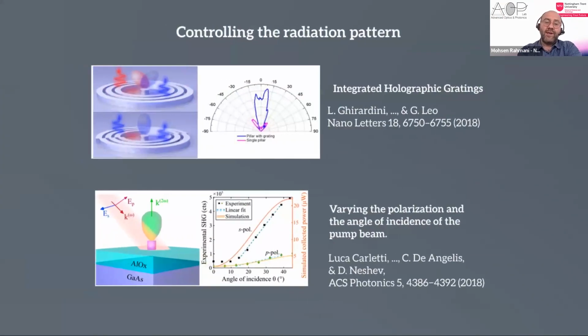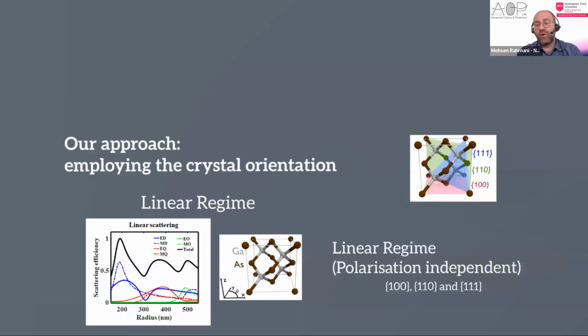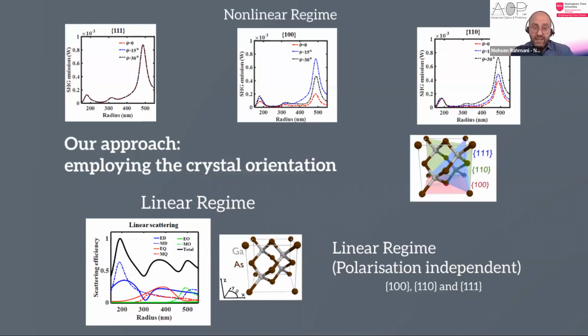So that's why there have been several efforts to solve this issue by using some grating around the nanostructures, or by using oblique incidence to have the nonlinear signal in the normal direction, so that we could solve this issue and we could use them. And there was another strategy proposed by us to use different crystalline orientations of III-V semiconductors to solve this issue, because most of those studies which I mentioned in the last few slides were using the 100 crystalline orientation, and we showed that by using other crystalline orientations like 111 or 110, we really can control the nonlinear emission here.